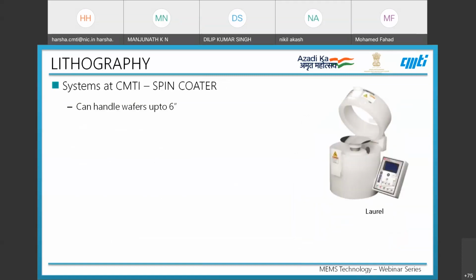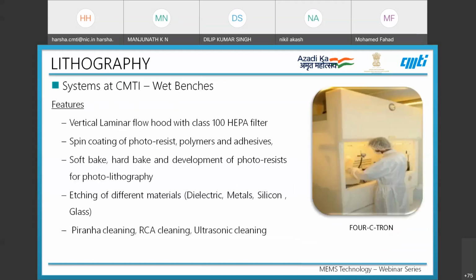We also have a spin coater which can handle wafers up to 6-inch from Laurel. Then there are wet benches, where all the baking, development, and cleaning processes are done under fume hoods. They come with a vertical laminar flow hood with a class 100 filter, and even spin coating of photoresist is done inside the wet bench.